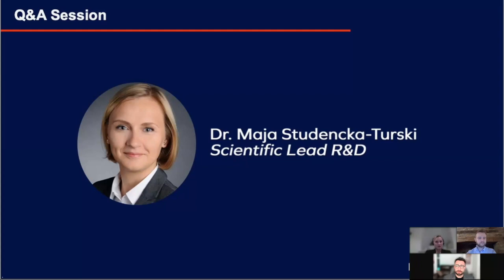If we take, for example, PlexTag as an example, PlexTag has a Taq polymerase inside. So as you probably know, Taq polymerases are able to process around 1 kb in 60 seconds. What we tested was an annealing extension time of 5 seconds, and it works. However, you always have to think about the size of the amplicon.